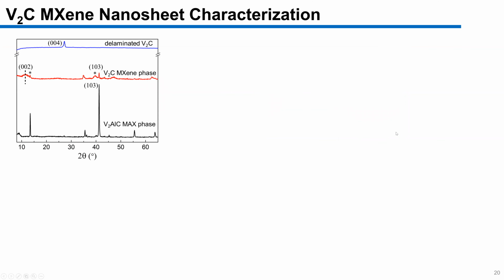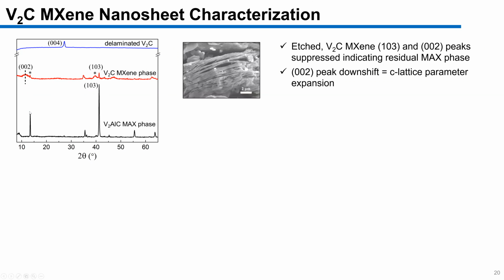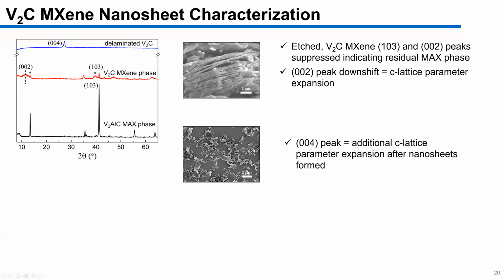So once we formed the MXene, we wanted to verify its morphology and crystallography. So we used X-ray diffraction, that's the spectra shown here, of the different stages of V2C nanosheet formation. The bottom spectra is for the starting material, the MAX phase material. When you etch away the aluminum layer, you get some peak suppression and peak shifting. And the peak shifting, shown with these little asterisks here, corresponds to a c lattice parameter expansion. So that is the expansion that results when you remove the aluminum layer. And then when you do the intercalation step and the sonication step to form the nanosheets, you get additional c lattice parameter expansion. And we expect that, you're essentially just stretching the material to form these nanosheets.